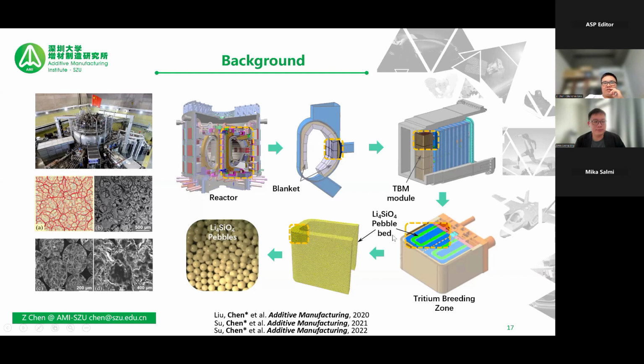This kind of bed configuration is not good enough because there are two main issues. The first one is that the pebbles contact each other with point contact. So at high temperature, there will be stress concentration. This is not beneficial to long-term durability. The second issue is that the stacking of the pebbles has a geometric limit, for example about 70% packing density, and we cannot go even higher. So this will limit the tritium breeding efficiency. Based on this observation, we try using lithium orthosilicate material with 3D printing